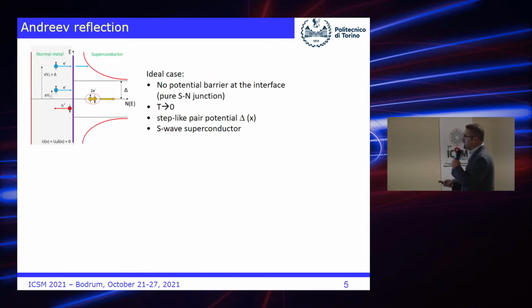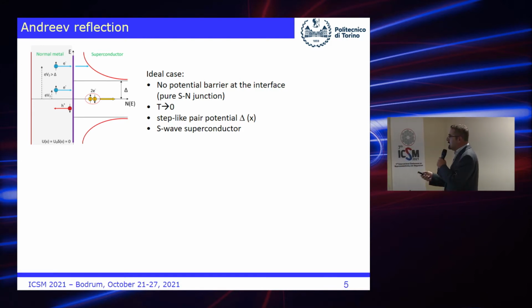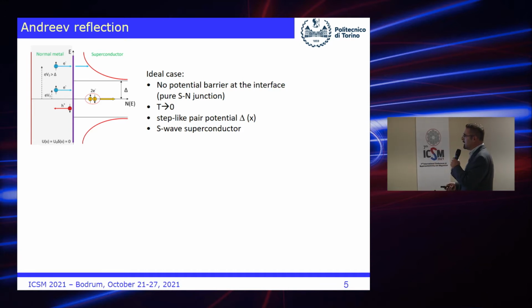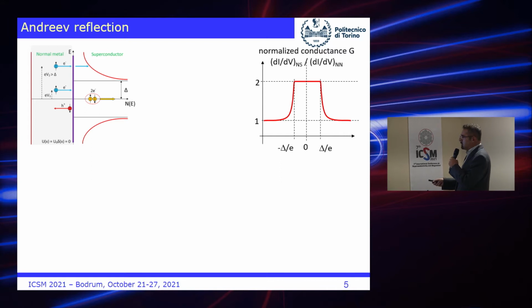So what is Andreev reflection? Very briefly, suppose you have a normal metal in direct contact with the superconductor. Direct contact means suppose that there is no potential barrier at the interface, then you apply a bias voltage to the junction and you obtain a current. What happens at the microscopic scale? The electrons that have an energy smaller than the gap on the superconducting side cannot propagate as quasi-particles, clearly. So there is the formation of a Cooper pair and a hole is reflected back. This is Andreev reflection. While the electrons that have sufficient energy to be transmitted in the superconductor are simply transmitted as electron-like quasi-particles.